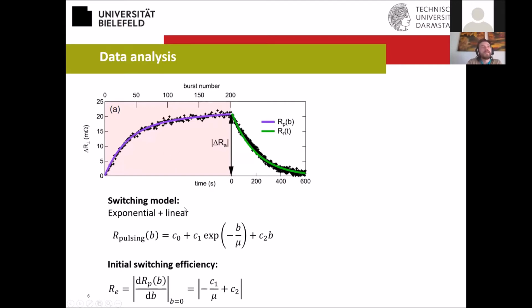And then we apply a simple switching model, which is simply phenomenological. We just fit an exponential here and add a linear contribution. And this allows us to take the derivative here for the first few pulses very, very accurately by just looking at the analytic form of the fit. So we can look at the efficiency of the switching, which is basically this derivative here, by just looking at the coefficients of the fit.